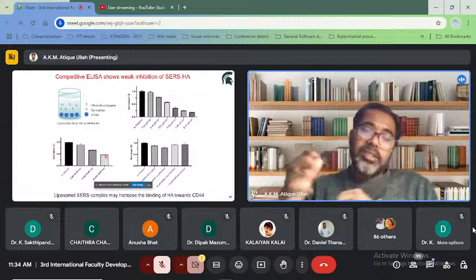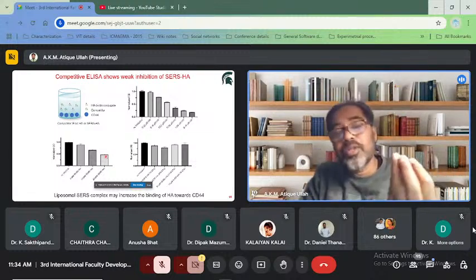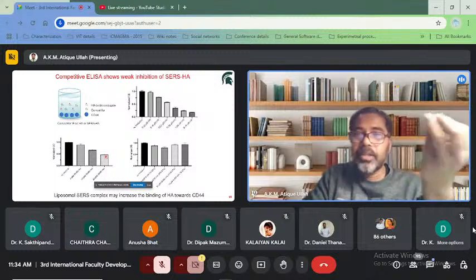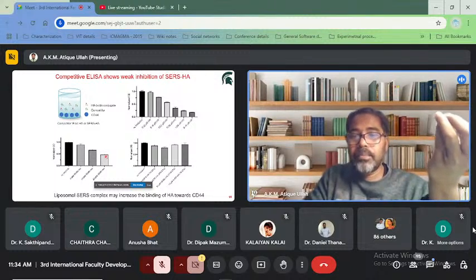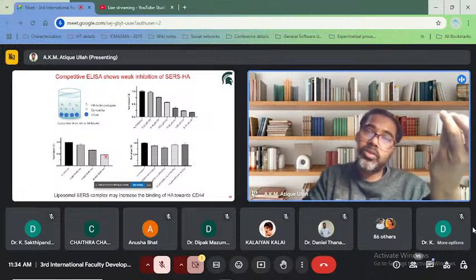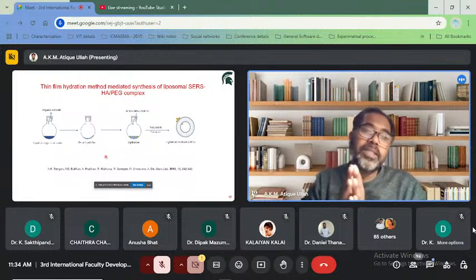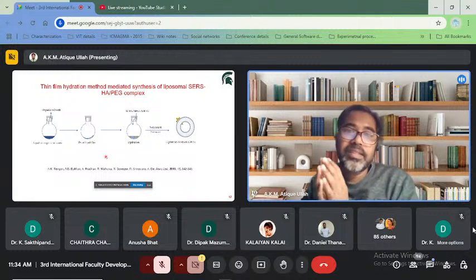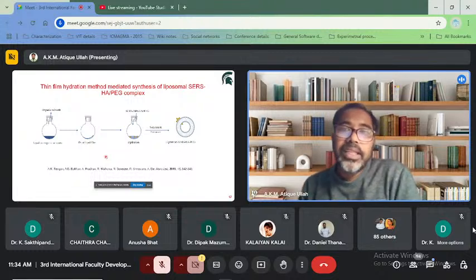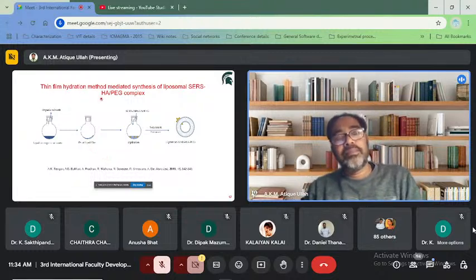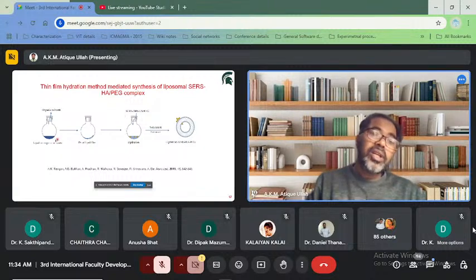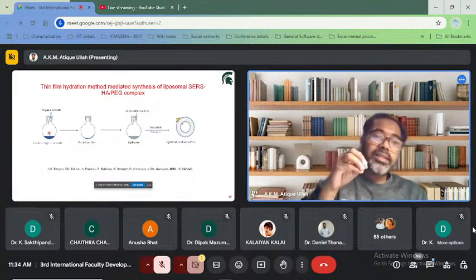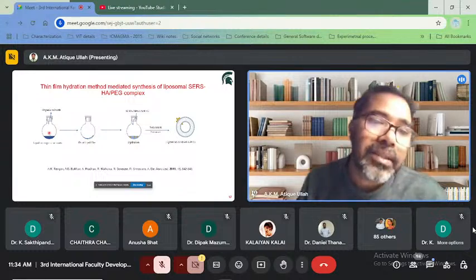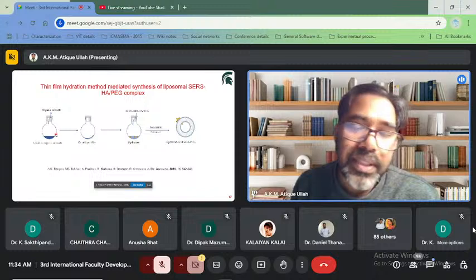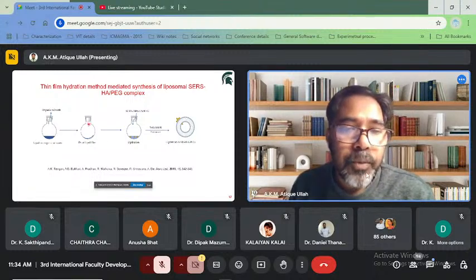the SERS nanoparticles with the liposome, because we know liposome is a biocompatible biomaterial, and it can also act as a passive targeting. So we formed a SERS HA or PEG complex with the liposome using the thin film hydration method. In this method, we dissolved the lipid and the cholesterol in a co-solvent organic solvent, that is chloroform-methanol. We dried it.